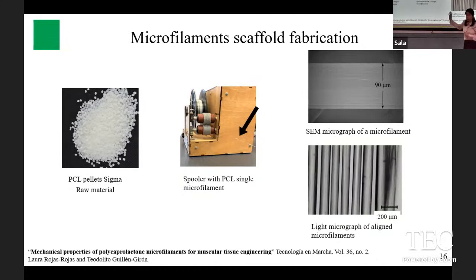In this case, we wanted to imitate a skeletal muscle, which is made as parallel grouped fibers. So for that, we reproduced that configuration by using PCL pellets extruded with a 1 millimeter die and collected in a spooler. Then we did some characterizations of the surface of the sample, and also we saw that they could be arranged parallel to each other. The average diameter of the microfilaments that we obtained was 90 micrometers.